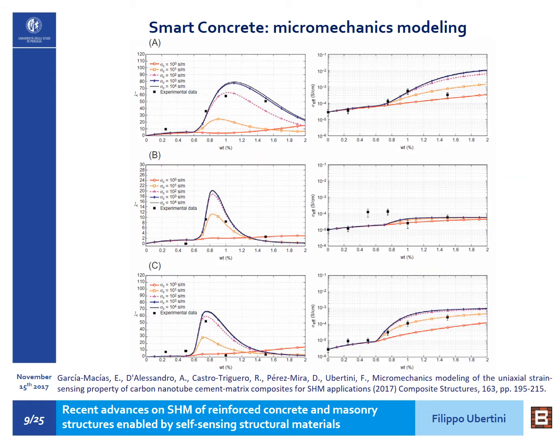So here we see some results of the application of the proposed micromechanics framework. On the top you see results referring to cement paste with carbon nanotubes. In the middle part of the slide you see results referring to cement mortar with nanotubes, and on the bottom part of the slide you see results of concretes with carbon nanotubes. The diagrams on the left show you gauge factor against the amount of nanotubes in the composites, and on the right you see the overall electrical conductivity of the composite against the amount of nanotubes. With the different lines you see results referring to different values of the conductivity of the nanotubes, and with black squares you see experimental results achieved in our lab.